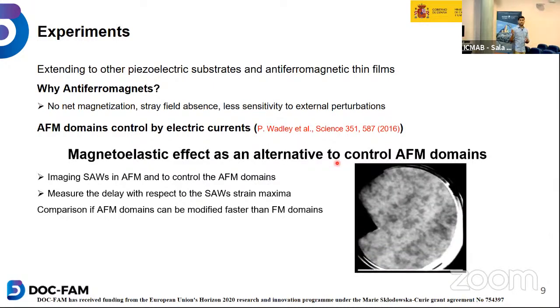This was our first goal. Then measure the delay with respect to the SAWs' strain maxima. That has been done already with ferromagnetic material, so we want to see if it's possible in antiferromagnetic domains as well, and if it's faster than in the ferromagnetic domains. So these are the domains. You can see we have just done this experiment recently, and we see here some domains.